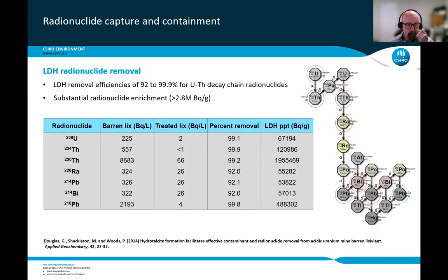Now, if we look at the radionuclide removal, and again, another really interesting story, in summary, we remove anywhere between about 92 and about 99.9% of the uranium-thorium decay chain radionuclides. I've got the uranium decay chain there on the right, and all of those circled either in the green or the red are the particular parts of the decay chain that we looked at. And if you look at the radionuclides down in the table there, in the first line, we've got everything from uranium-238 at the top of the chain to lead-210 at the bottom.